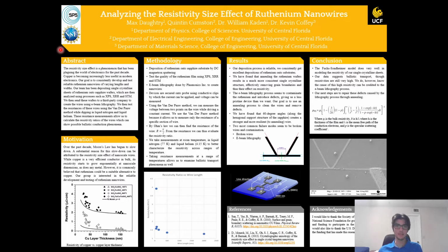So this effect for copper is very great. The copper's resistivity starts to grow very quickly as it approaches nanoscale dimensions, especially compared to other metals such as ruthenium. So there's actually a point where copper's resistivity crosses ruthenium's, and the resistivity of copper becomes greater than that of ruthenium. So it's pretty widely believed at this point that ruthenium is a suitable replacement for copper in the coming years. So our group's main goal is to reliably develop and test resilient ruthenium nanowires.